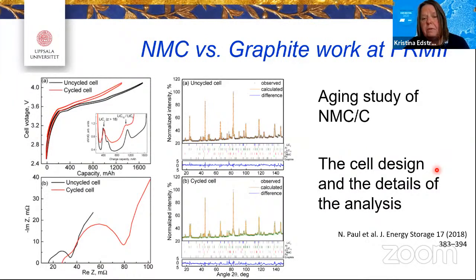Another example, also from FRM2, is an aging study of NMC versus graphite, where you can really see how the lithiation of the graphite is influenced by the long-term cycling and also the impedance of comparing the uncycled and the cycled cell. And you can really see subtle details in the diffraction pattern. And I think the refinement of these is really nice. And what I would like to highlight here is this detailed, mechanistic understanding. But at the same time, the cell's design is made by a company and it's looking almost like a real commercial cell.